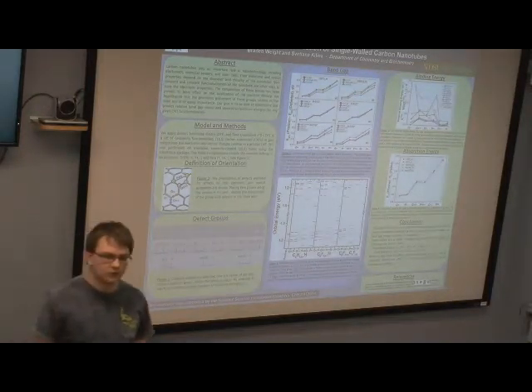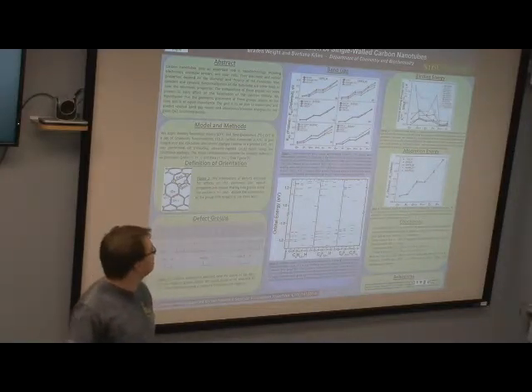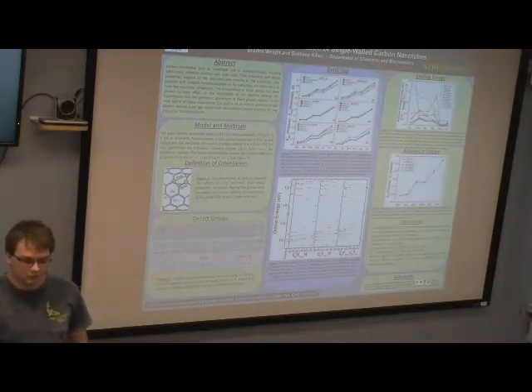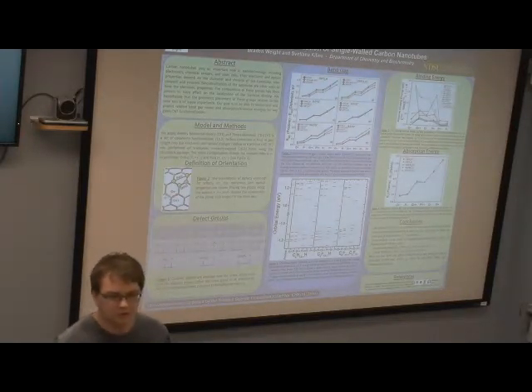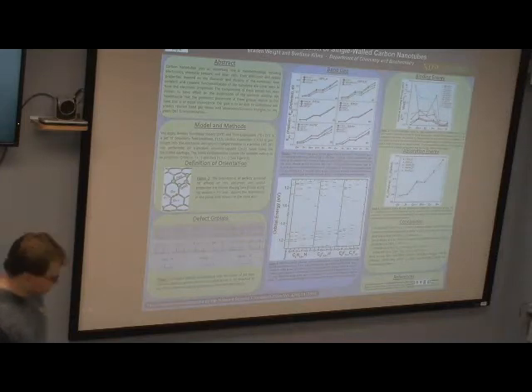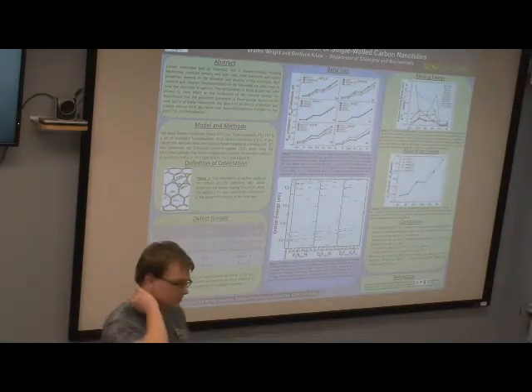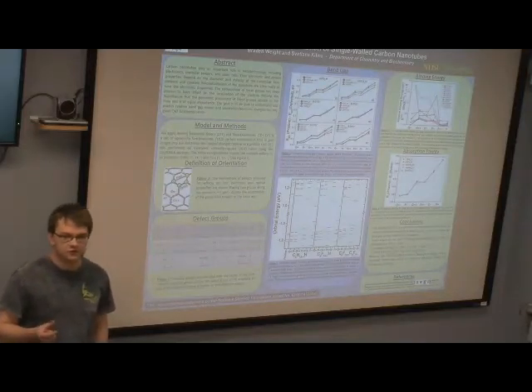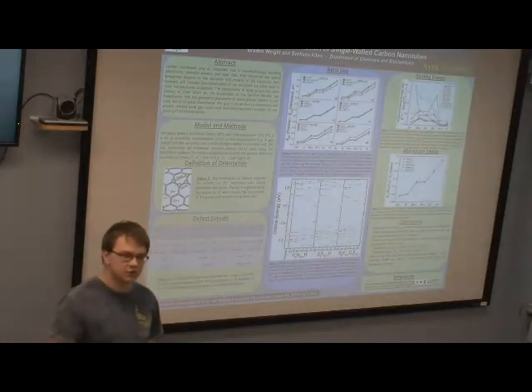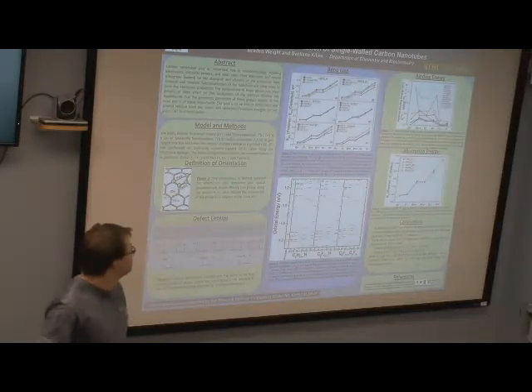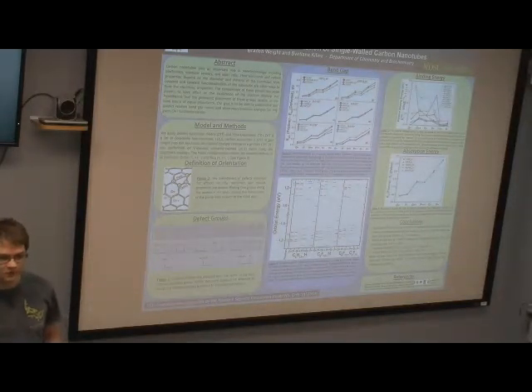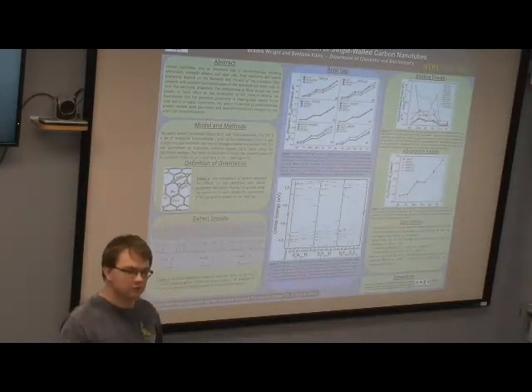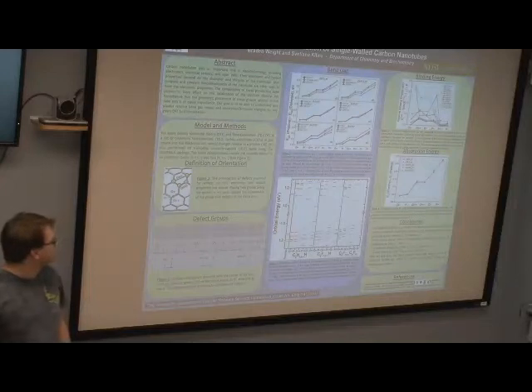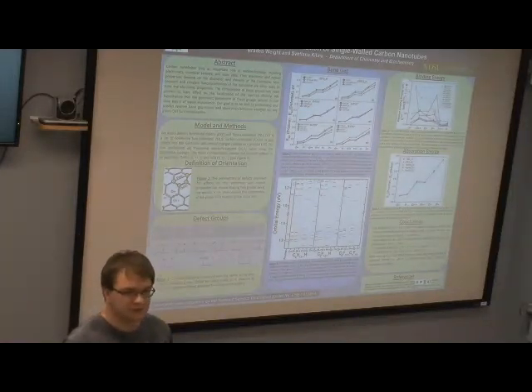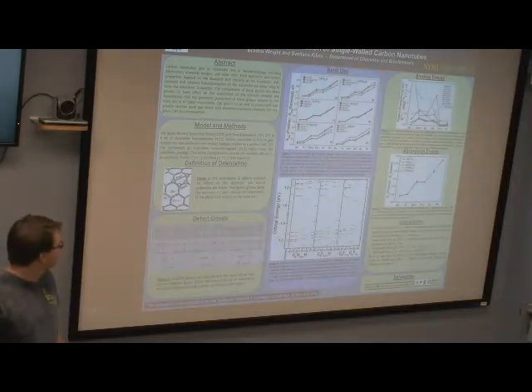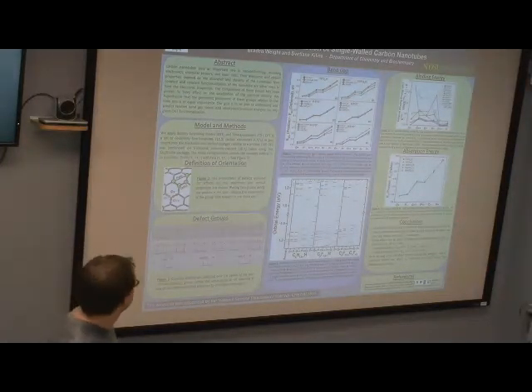Another way to do this, more recently, is covalent functionalization of the carbon nanotube for more specific fine tuning, I guess you could think of it as. So what we're doing is taking a bunch of different functional groups and covalently attaching them to the surface of a carbon nanotube to cause a hybridization defect, from sp2 to an sp3 type hybridization. And we'll need to do two defects on the carbon nanotube at a time to get away from the open valence you get from just doing one.